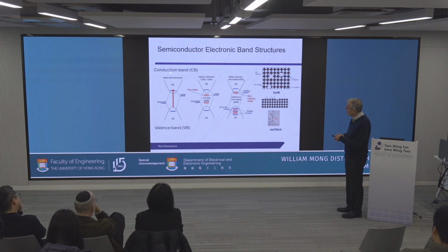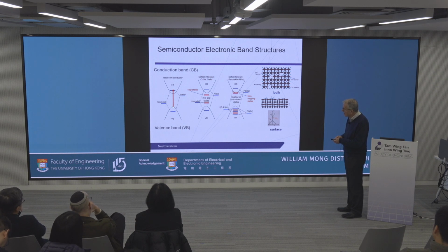Now, why is this important? These are just cartoons of band structures of conventional semiconductors like silicon and perovskite. They look very similar. There's a conduction band and there's a valence band. However, in this bonding arrangement, silicon, germanium, gallium arsenide, cadmium telluride, if you have a defect here, like a vacancy or an anti-site defect or something else, a state comes off and moves into the gap. And the same here. If you have some kind of defect, an impurity, a state comes off and comes into the gap. These are trap states.